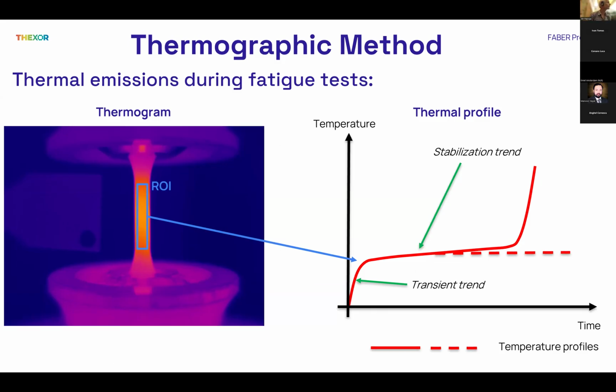As I said before, the thermographic method is an alternative approach to the classical staircase methodology for the fatigue limit assessment, and this methodology adopts the thermal emissions produced during the fatigue test. This slide reports an example of a thermal profile obtained from the thermal emissions. This thermal profile is extracted from a region of interest located over the surface of the sample from the thermogram. This thermal profile is characterized by a transient trend followed by a stabilized trend. This stabilized trend may remain stable in case of a stress amplitude lower than the corresponding fatigue limit of the material. On the other hand, this stabilized trend may increase its evolution with a rapid temperature increment in case of a stress amplitude higher than the corresponding fatigue limit of the material.